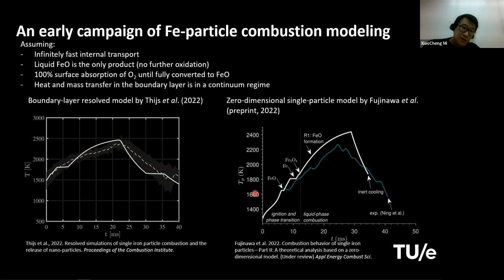But from both of these results, there are some things that we need to remark. Some obvious disagreement with the experimental data. One thing is the heat-up process seems faster than the experimentally recorded data, although the experimental data also have some error bar, some uncertainties there. And the other thing is, since we stop the reaction after everything is converted to FeO, the cool down seems to be much faster than the experimental data, right?